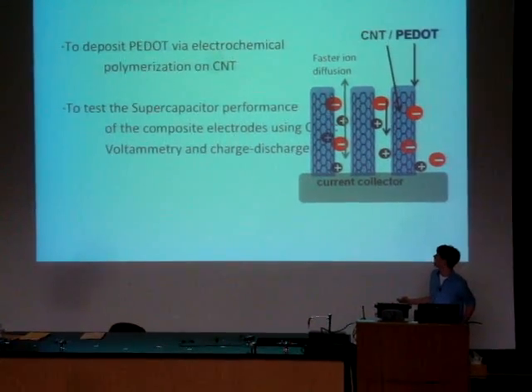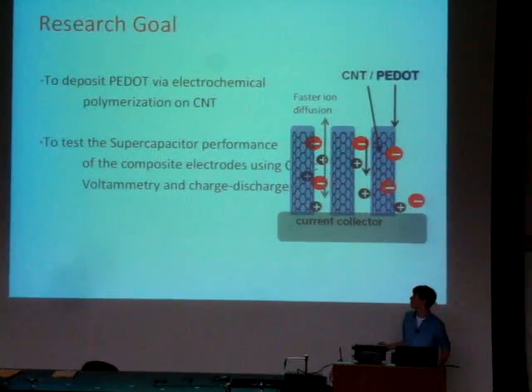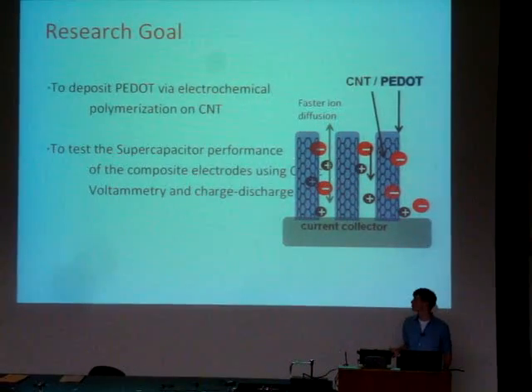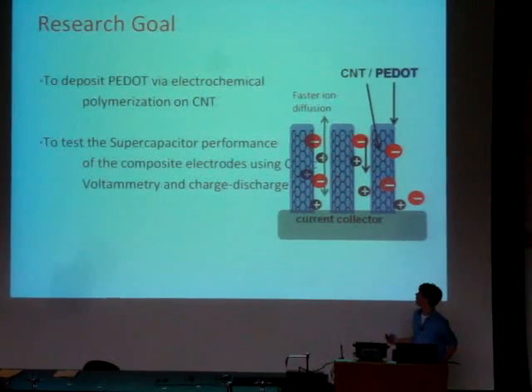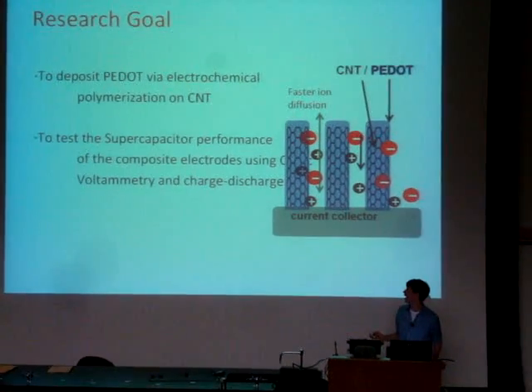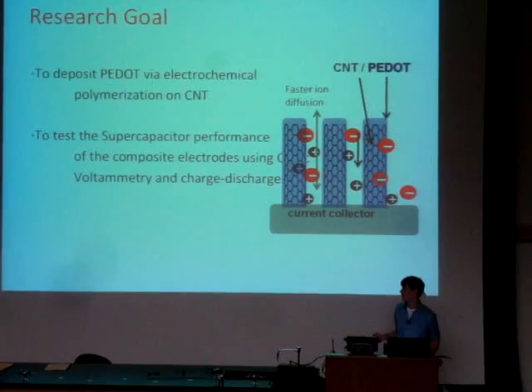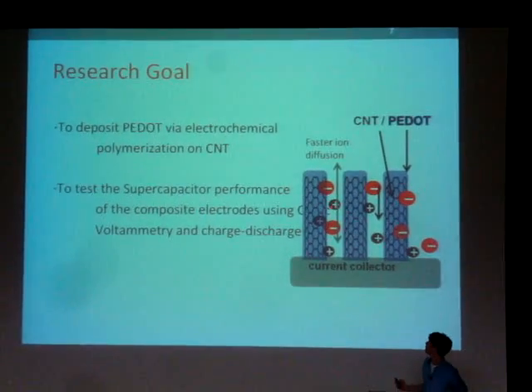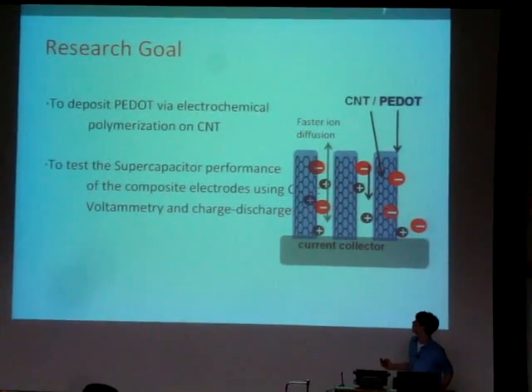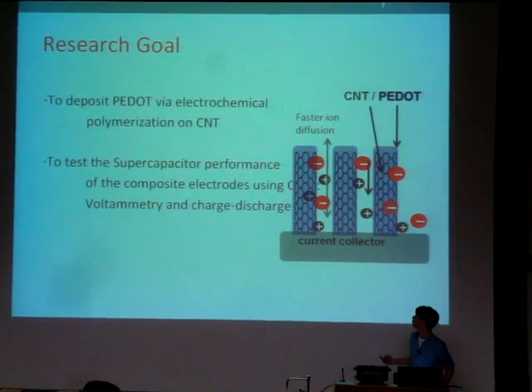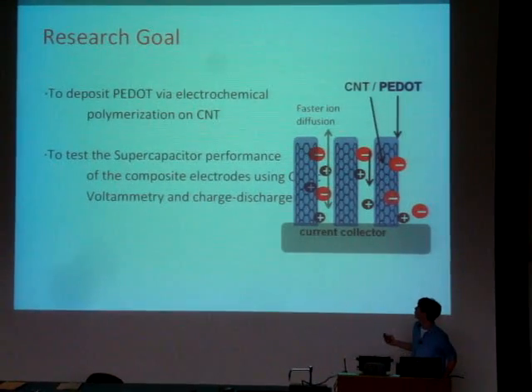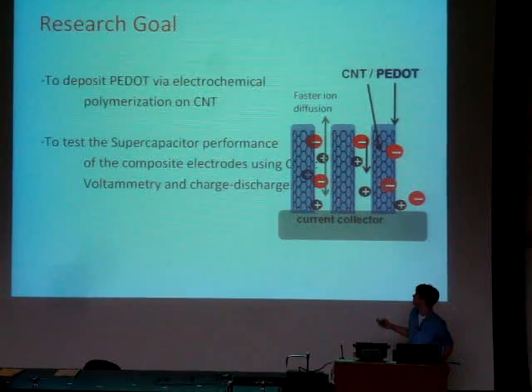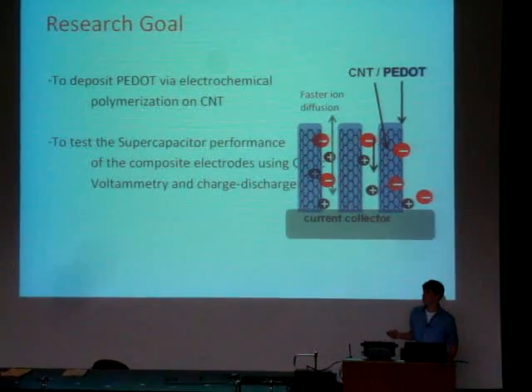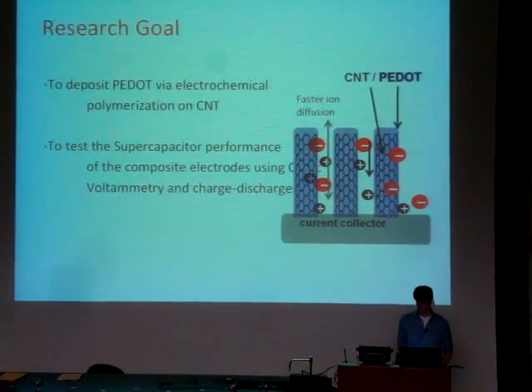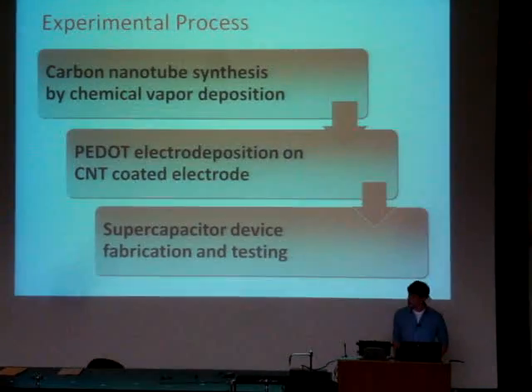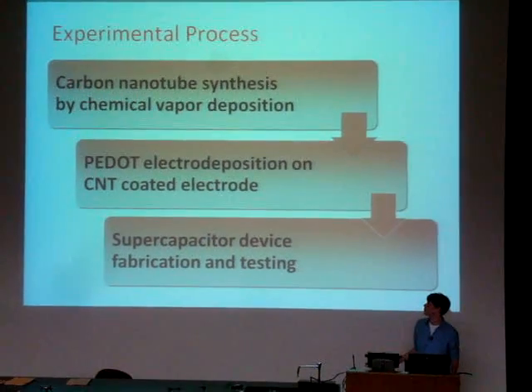We used both the carbon nanotubes and the PEDOT to enhance the electric double layer and pseudocapacitive properties. The carbon nanotubes are extremely porous, and that enhances the ion diffusion, which raises the power and helps the electric double layer properties, through faster ion diffusion. Also, the carbon nanotubes served as a backbone for the PEDOT to be deposited, and when deposited, it allows it to be de-doped and doped along the surface, which raises the pseudocapacitive properties and raises the energy density.